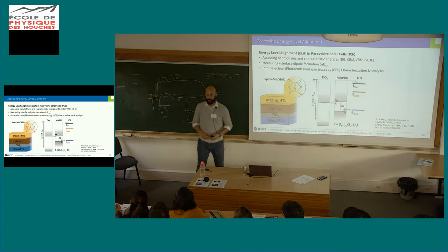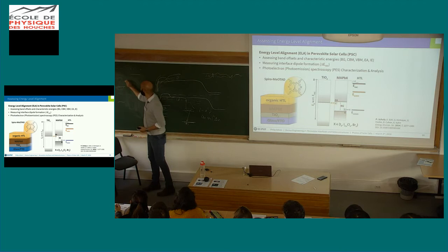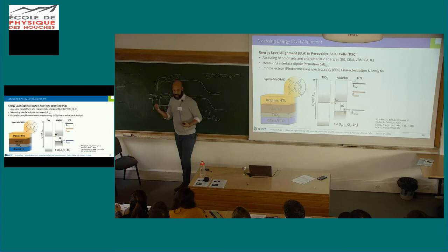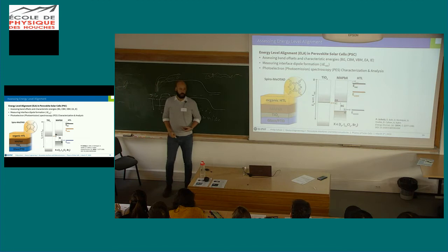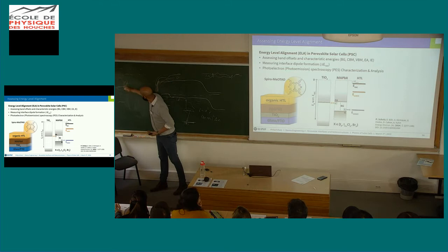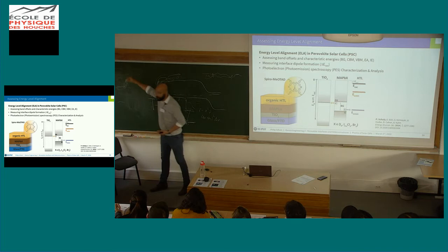Okay. So, could I simply go ahead and draw it like this? No, and actually I cannot, and the point is really in here, because now you have occupied states over here that are higher in energy than unoccupied states here, and what you effectively get is transfer of electrons to the acceptor. This will eventually pull down the entire thing, including the vacuum level, that gives you this dip over here, which constitutes an interface dipole. Okay.